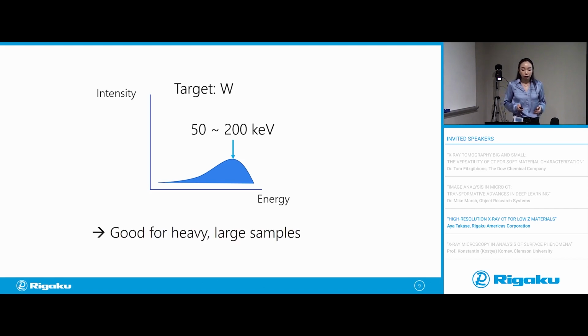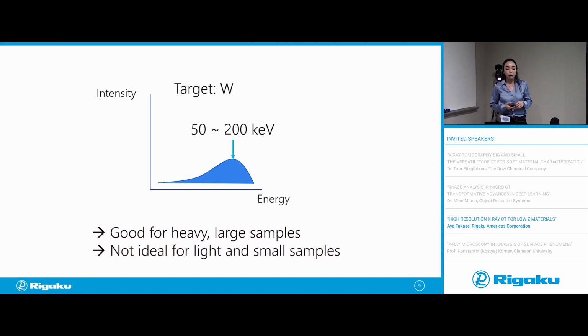That is really good if you want to look at heavy or relatively large samples. You can use it for medium density, medium sized samples as well. But tungsten is not the best target to use to image low Z materials because you have to lower the applied voltage to shift that peak towards the lower side. And when you lower the applied voltage too much, you lose too much X-ray intensity. So there is a limit of how low you can go with the tungsten target. This is not an ideal material for an X-ray target if you want to image light and small samples.